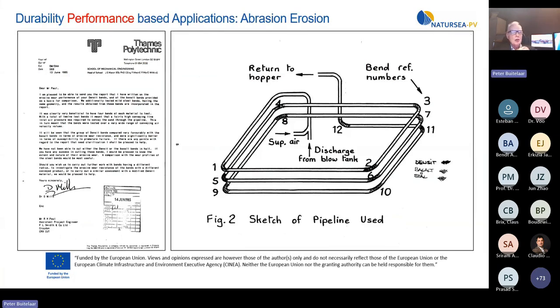Abrasion erosion or cavitation erosion is a large problem in the industry when abrasive materials like silica sand, coal, cement, glass, etc. are hydraulically or pneumatically transported in systems with high velocity in huge amounts. No test method can simulate the very complex phenomenon of the actual wear in a system. Particle size, hardness, dimensions, angle of impact, temperature and speed all contribute to the abrasion of materials.